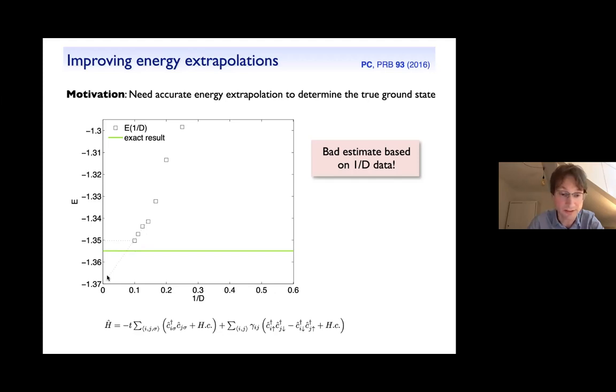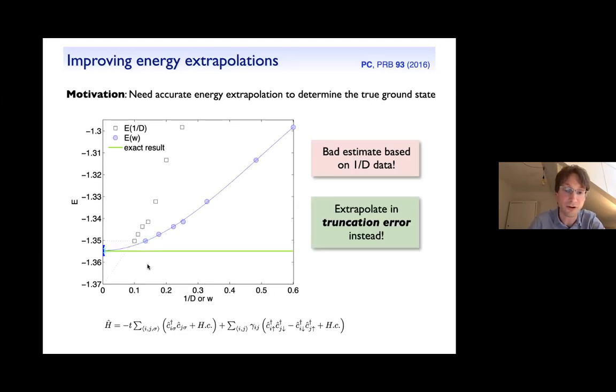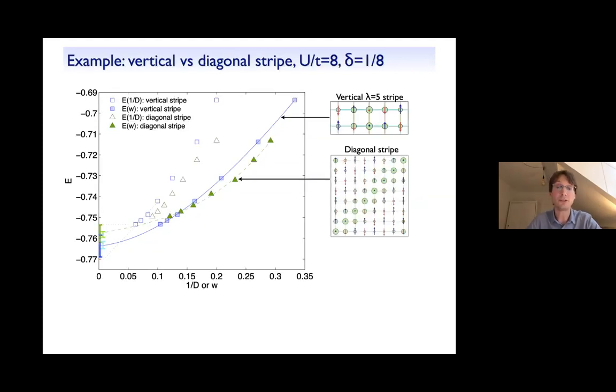But one way to improve this is, instead of plotting as a function of 1 over D, we can also plot it as a function of a truncation error. So this W here, that's the same data, but plotted as a function of the truncation error. That's a quantity which is often used also in DMRG calculations, and here we have defined it in the context of the imaginary time evolution algorithm. But in the end, it's also a quantity that goes to 0 in the exact case. And here we find that if we use this data and extrapolate, we can get the extrapolation more accurately than in the 1 over D case. Okay, so let's use this technique now to compare the energies of these competing states.